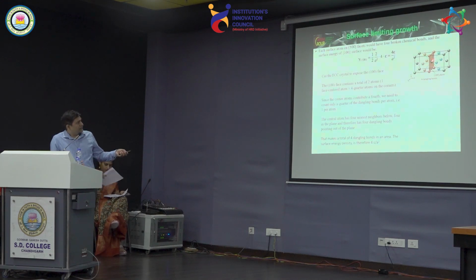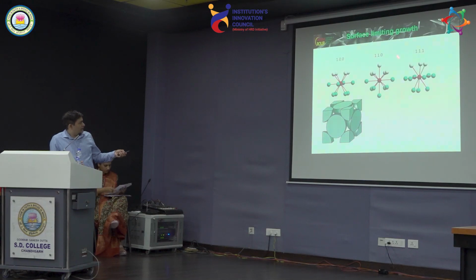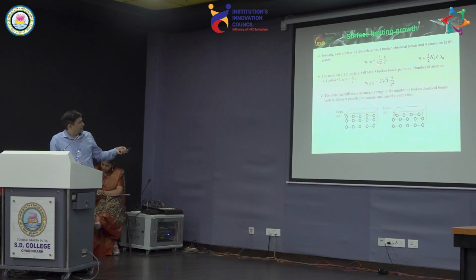You can see the number of atoms, the dangling bonds, like it is a 4. You can put all these in, and the differences in the dangling bonds on different planes and the density difference all lead to the surface energy difference. That's why even if you have a cubic system, when the vapors are condensing on the substrate, they will start to grow in different directions.